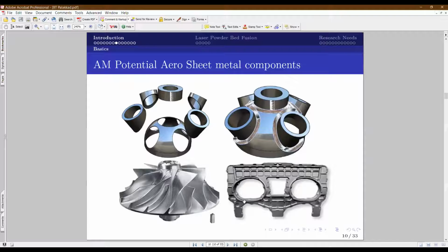And some of the components in the aircraft, like the impeller, are directly machined from bar stock due to the complexity of the shape. In this case, a 100 kg metal bar stock is taken and machined to get this impeller, which is 5 kg. So you can see 95 kg of the material is wasted. Such a poor yield process can be replaced with 3D printing, and the complex shapes can also be easily achieved